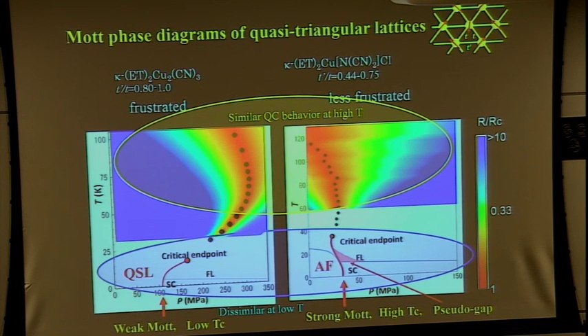If you measure the critical exponents, are they the same as the critical point? Yeah, that's a good point. It's controversial. Yes, gas-liquid critical universality: the gas-liquid transition belongs to the same universality class as Ising. But we determined the exponent, and it is different. Still, it is controversial. Some other groups reported that the critical exponent is exactly the same as the gas-liquid transition. So it is controversial, yes.